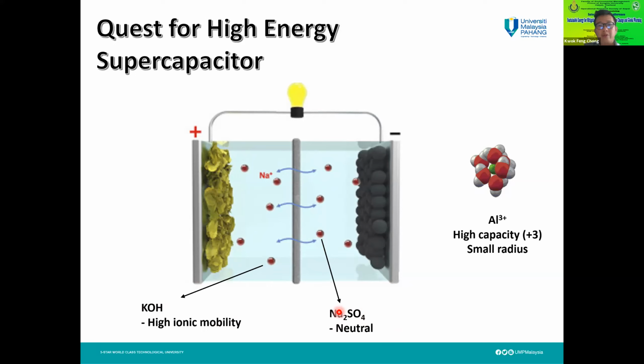So I threw my group members a challenge. We know that the aluminum ion, aluminum 3+, has a very high charge capacity, because each hydrated aluminum ion, one atom of this aluminum ion, actually has 3 charges. It has a very high charge capacity of +3 as compared to the rest, which are potassium +1 and sodium also +1. At the same time, it has a very small radius. So we can benefit from this. Imagine that you have a piece of paper and you want to absorb aluminum ions onto it. As compared to the rest, you can absorb a lot because it has a very small radius. And at the same time, it has a very high capacity, because one ion that you absorb is equivalent to 3 ions of the other electrolytes.